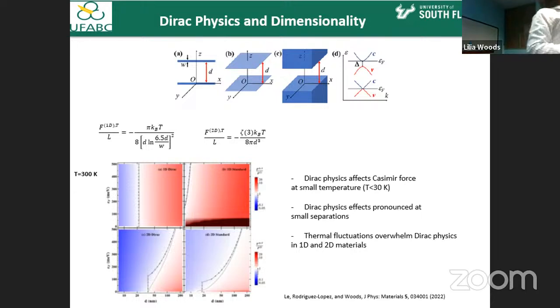In other words, I'm not looking exactly at the quantum regime at temperature 0, but I turn on the temperature. Everything after 30 Kelvin is masked by the classical thermal fluctuations. And this is true for 1D Dirac material, 1D standard material, 2D Dirac material, 2D standard. Doesn't matter. So if I'm looking at a regular temperature, the topology type of material doesn't matter.